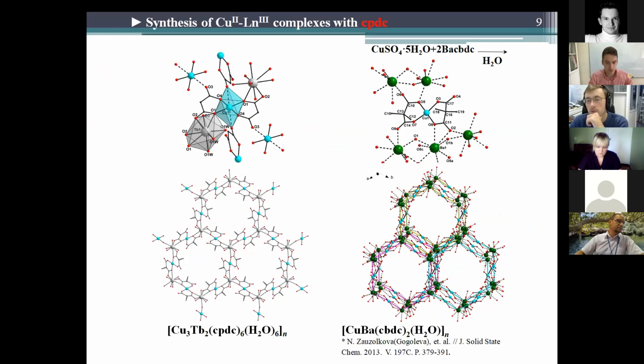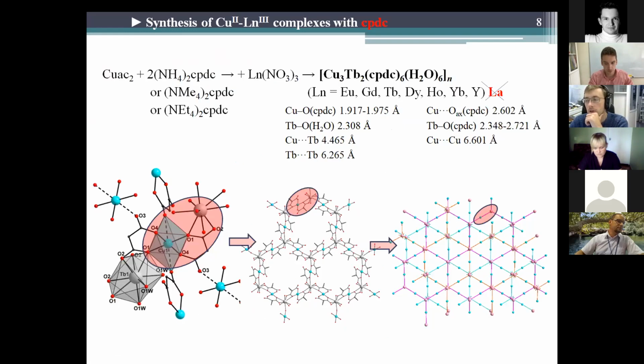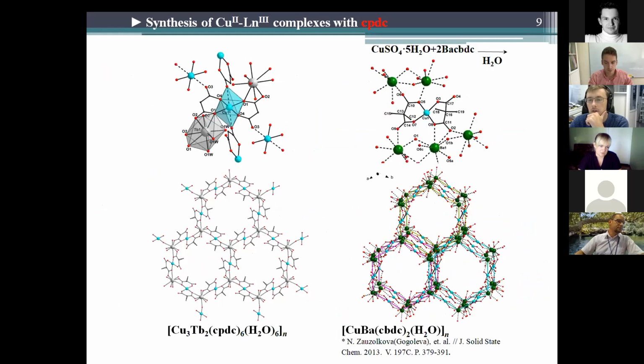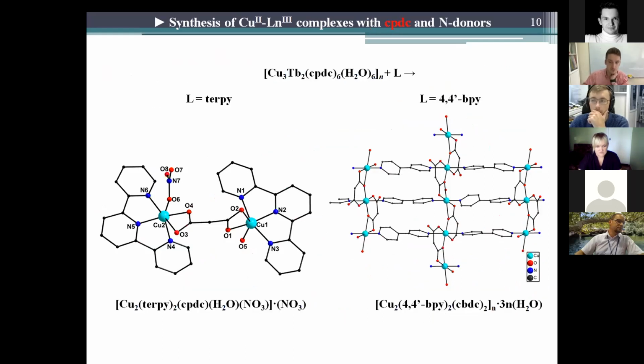We were able to synthesize this polymer with a range of lanthanides, except lanthanum. It appeared that they were all isostructural. A similar structural motif in crystal packing was found in copper barium cyclobutane dicarboxylate and dimethyl malonates. Only monometallic complexes were separated when we tried to add a donor ligand to the heterometallic system.